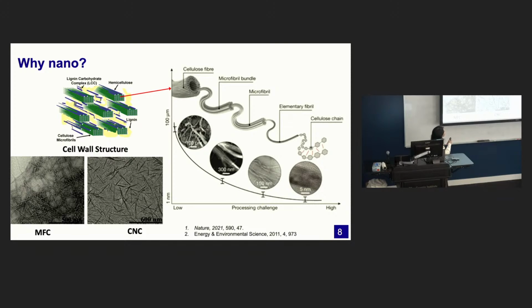But if you look at the cellulose fibers, they are bound together because, like for wood, they need this. We go against nature, because if we want to downsize the cellulose fibers, firstly they consist of microfibril bundles, and then you can further downsize to microfibrils and elementary fibrils, and then finally the cellulose chains. So you can get down to like 5 nanometers. But all this needs energy and harsh reaction conditions. Currently in the lab, people firstly use enzymes or chemical and thermal ways, so you can get microfibrillated cellulose. Or if you further use harsh conditions, you can remove the amorphous part of cellulose.